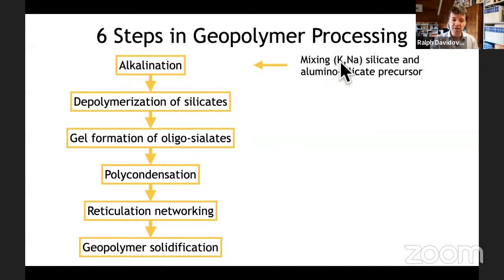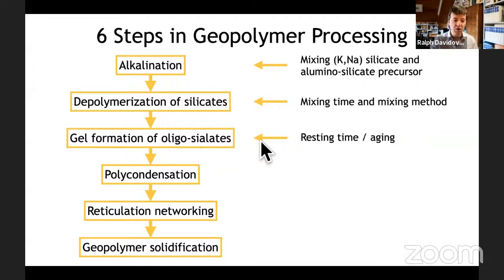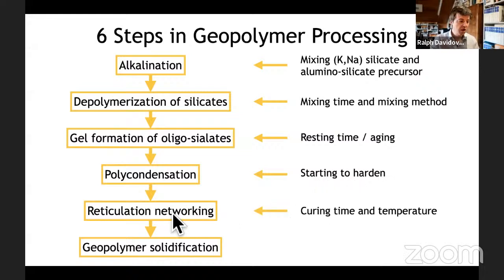Alkalination is the mixing of silicate and the aluminosilicate precursor. Depolymerization of silicate is the mixing time and mixing method. Gel formation of oligosialate is related to the resting time or aging if you need it. Polycondensation, it's starting to harden. Reticulation networking relates to curing time and curing temperature. Geopolymer solidification is the final hardening.